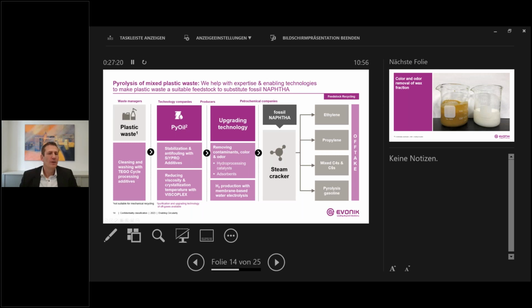So the plastic waste is converted into a liquid pyrolysis oil, and this pyrolysis oil is intended to be used in a steam cracker to replace fossil naphtha. The steam cracker produces olefins, so ethylene, propylene, butadienes, something like this. What we have seen so far is, as I mentioned, that the process is on paper relatively simple, in reality a challenging process because of, for instance, the contaminants. You have several different contaminants, chlorides, for instance, in the pyrolysis oil that need to be removed before it is managed in the steam cracker, because chlorides, for instance, are causing corrosion issues.